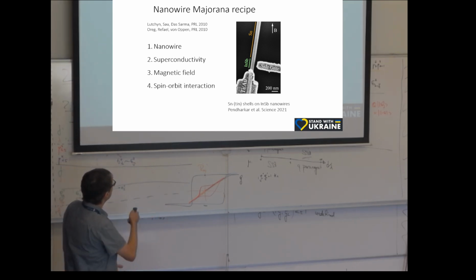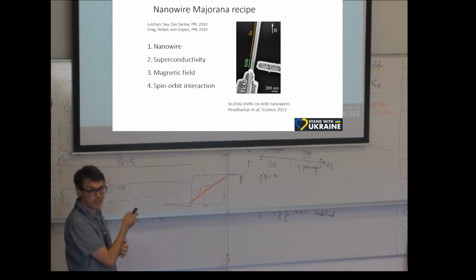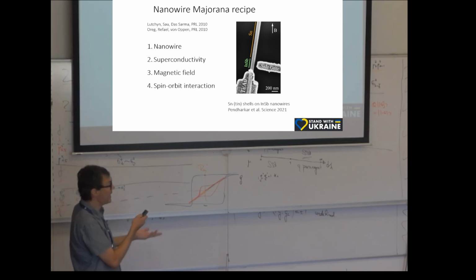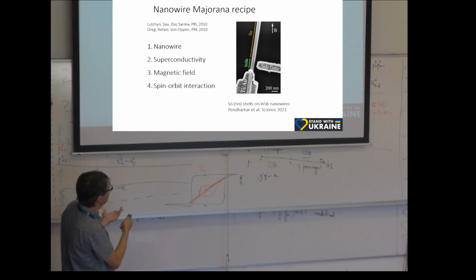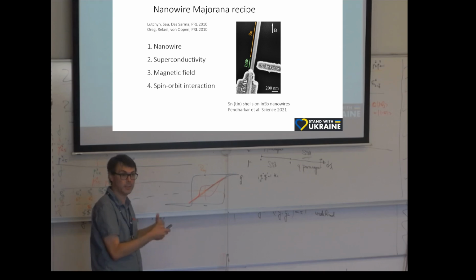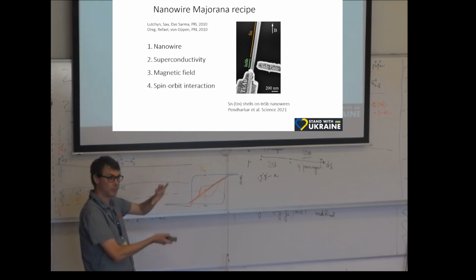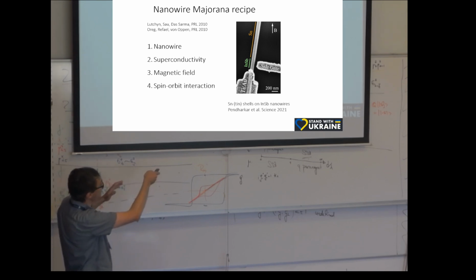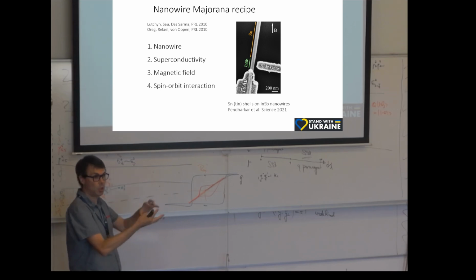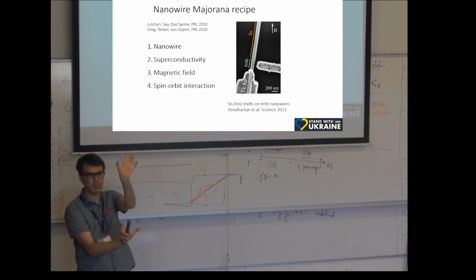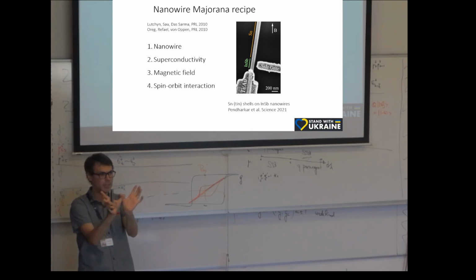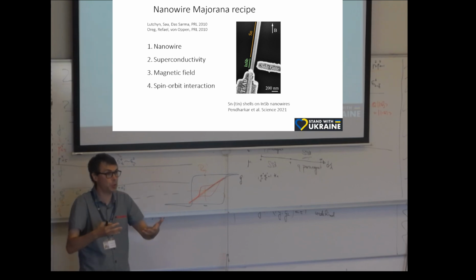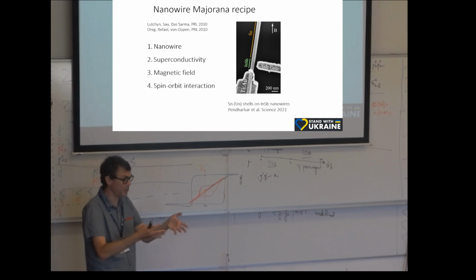So, superconductivity induced by proximity. We will talk about what that means. Then magnetic field, and spin-orbit interaction, which is an interesting ingredient. It's a property of the band structure where, in certain crystals that lack inversion symmetry, or where symmetry is broken by structure, like making an interface between a metal and a semiconductor, this term appears where the spin bands split like this, right? Zeeman effect, spin bands split like this. Spin-orbit effect, bands split like this, meaning depending on your spin, you have different momentum. So it is a spin-orbit term, analogous to atomic spin-orbit, if you remember it from your kindergarten physics, as you joke.